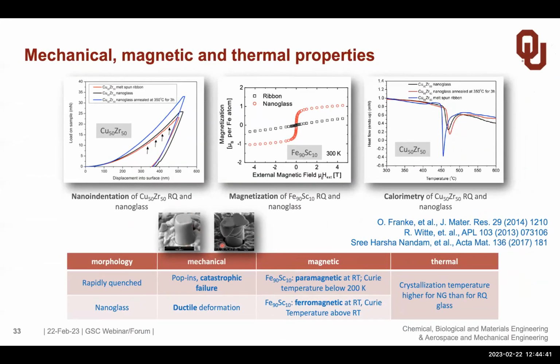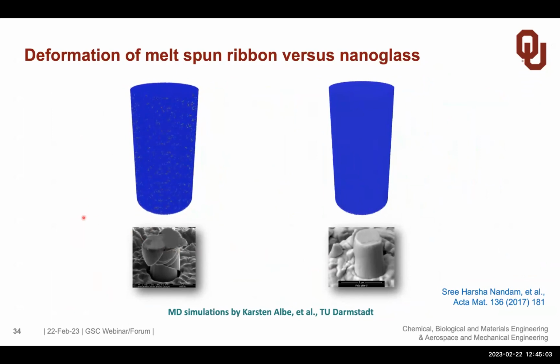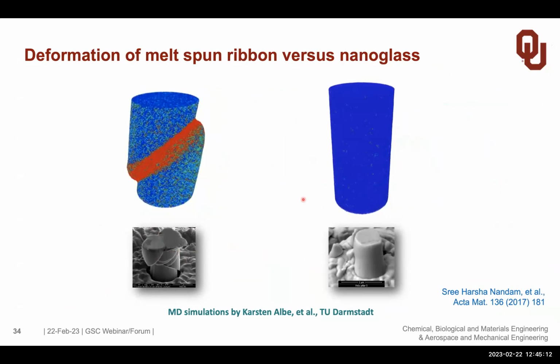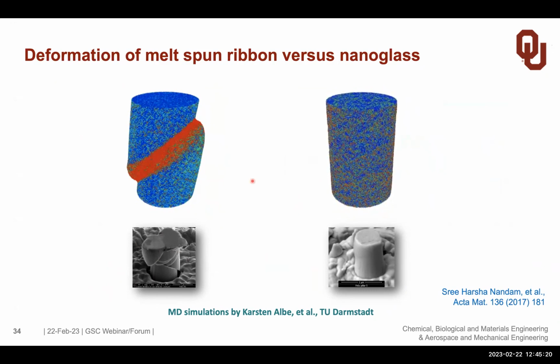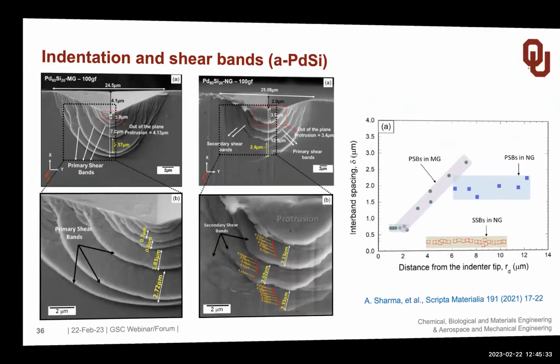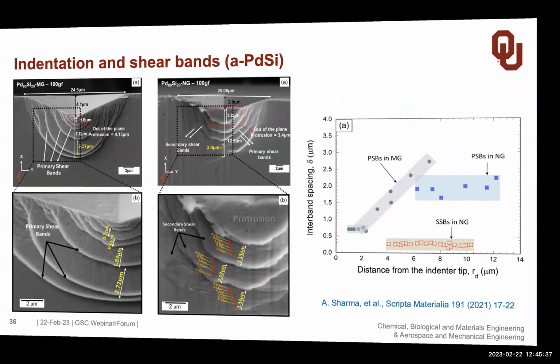And so this makes it interesting to look at, in particular also because we find different properties. For example, I showed you already that it becomes magnetic if we do a different processing, but it also becomes ductile instead of being brittle. So that makes it an interesting new material, maybe in the future. And I show you this also in these videos here of MD simulations. Here you see the catastrophic failure in a homogeneous glass. And here you see how it deforms homogeneously in a nanoglass material of the same composition as this side. So it has drastic changes of the properties of the material. And this is an MD simulation, but we can also do that experimentally. I also go over that because it shows detail of the shear band structure in these different materials.